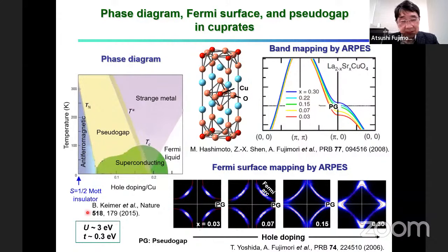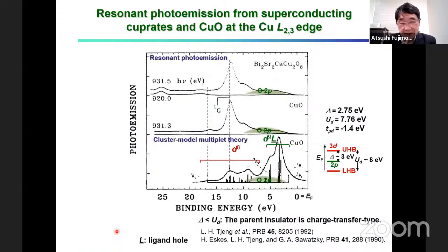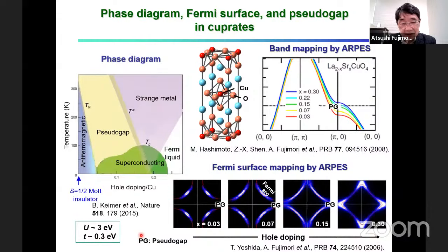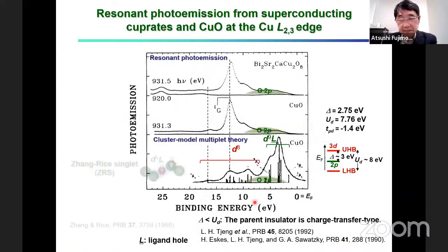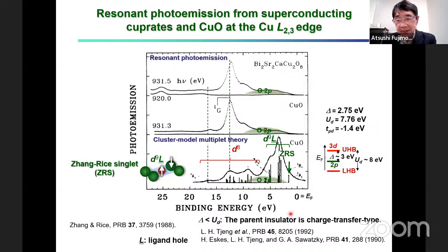And the single-band parameter is universally something like U equal 3, much smaller than this 7 or 8. And the hopping integral is also smaller than the bare hopping integral. According to this multiplet calculation, the lowest energy state is actually the so-called Zhang-Rice singlet, where the hole on the copper and the oxygen form a singlet within this square planar cluster.